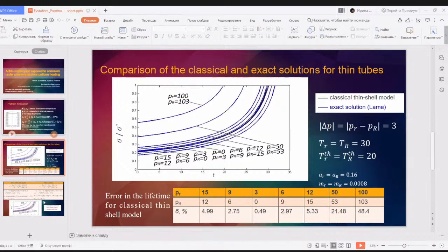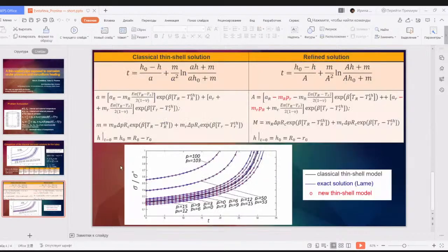We received a new solution in the form which is absolutely the same as the existing solution based on the classical thin shell model, with only constants being different. At the same time, our new solution reflects the effects of hydrostatic pressure, change in the hoop stress through the pipe wall thickness, and of the temperatures, and demonstrates a perfect coincidence of the results with the explicit solution, which is rather cumbersome. So that's all I wanted to say.